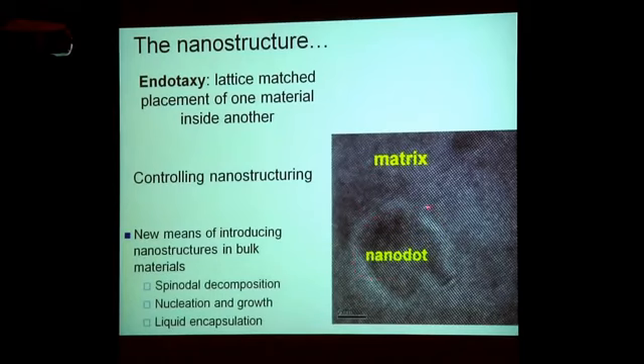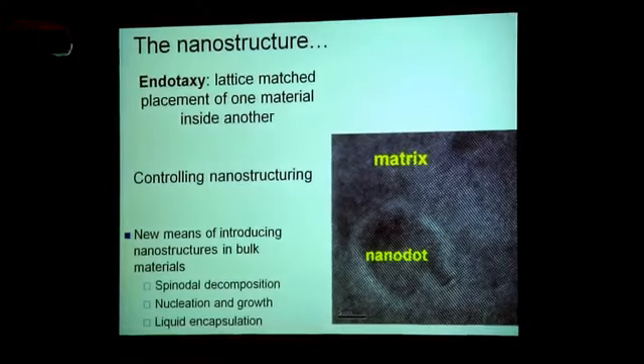We call this type of precipitation endotaxy, by analogy to epitaxy, because it is coherent and there's lattice matching. It's trying to lattice match in all directions. And so we think this is significant in the properties. This was a discovery. And it was important because later it changed the way we think about these types of materials. But we had to figure out ways to actually make these things on purpose. And we came up with 3 different ways based on spinodal decomposition, nucleation and growth, and liquid encapsulation.